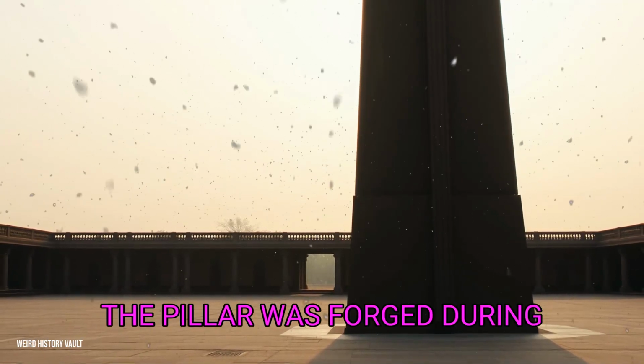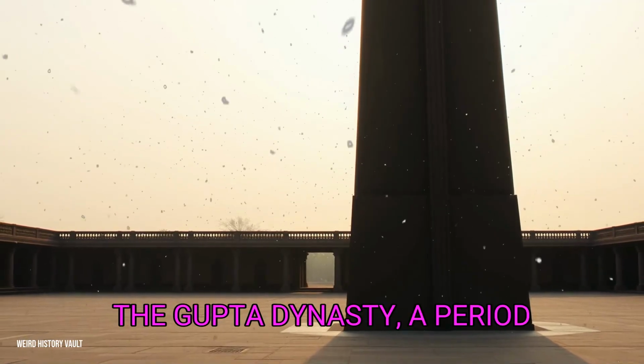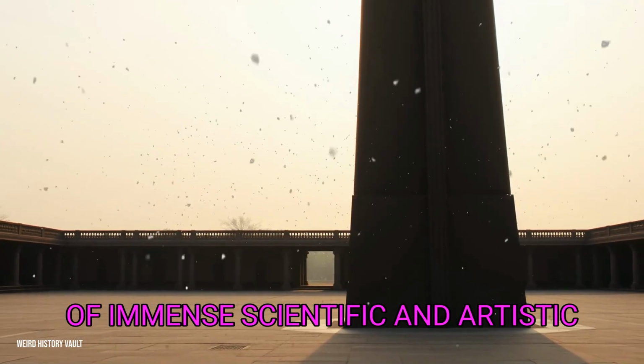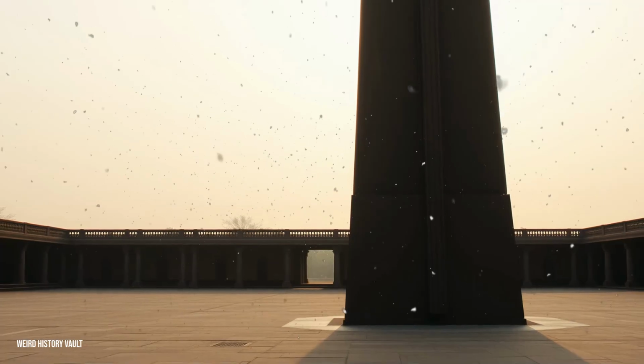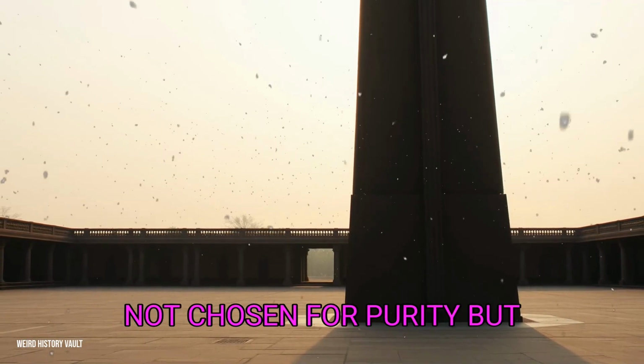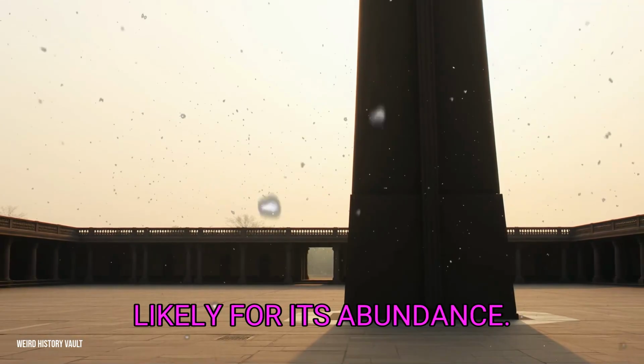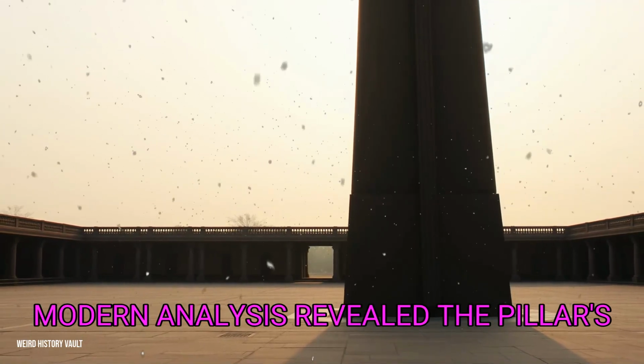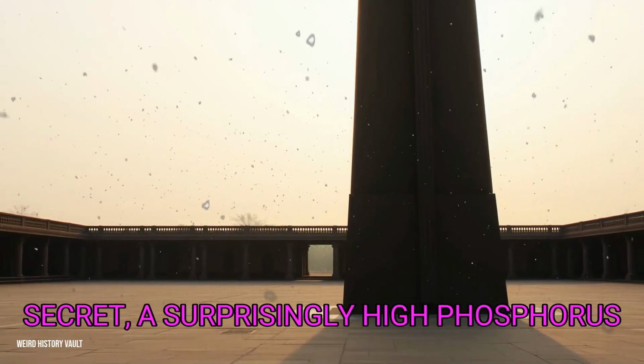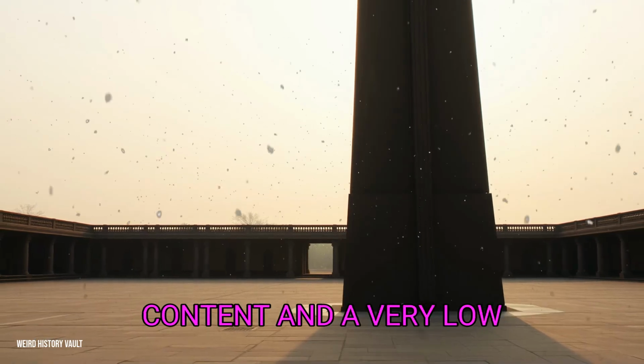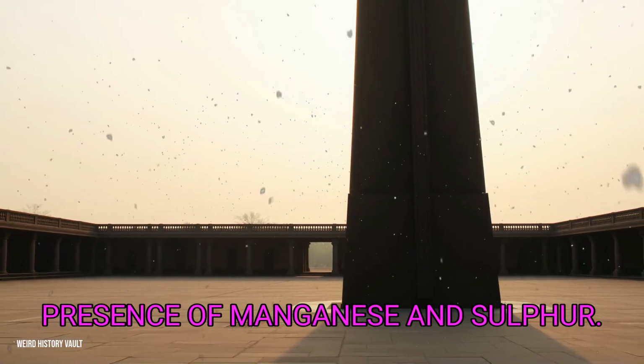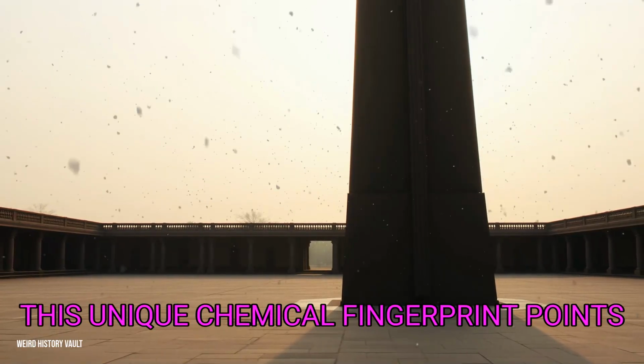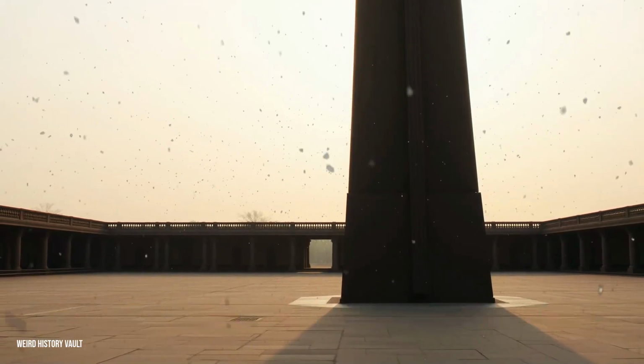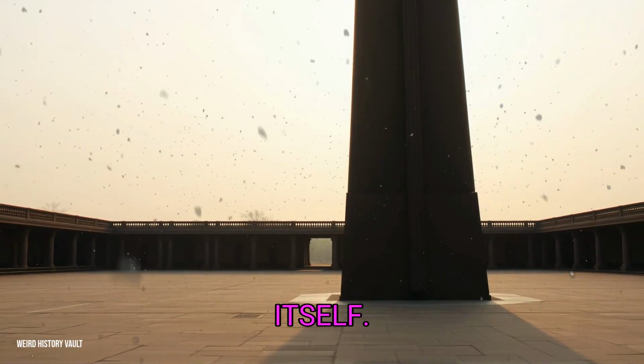The pillar was forged during the Gupta dynasty, a period of immense scientific and artistic achievement in India. The iron ore used was not chosen for purity, but likely for its abundance. Modern analysis revealed the pillar's secret: a surprisingly high phosphorus content and a very low presence of manganese and sulfur. This unique chemical fingerprint points to the forgotten smelting process itself.